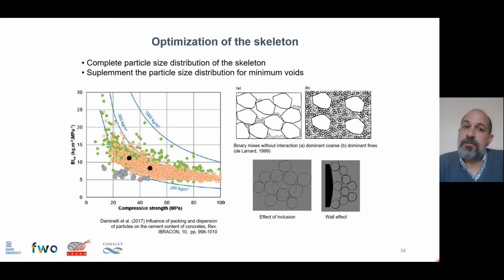And there's very interesting work done by the group of de Larrard in the last decade on the use of binder intensity and how to optimize it for compressive strength by working on the packing of particles, not only the aggregates, but also the fines. And by using fillers, they have demonstrated that we can obtain compressive strengths of 60 megapascals or higher with only 250 kilograms per cubic meter of cement. And this can effectively reduce the carbon footprint of concrete, not only in Latin America, but also worldwide.